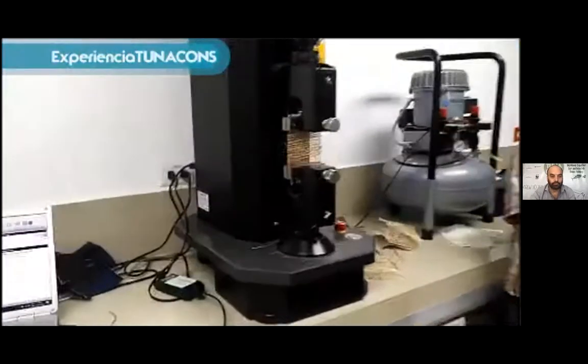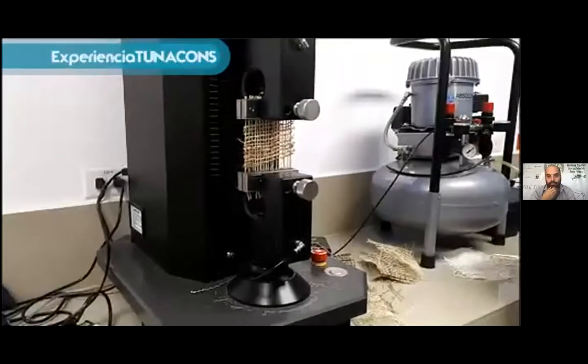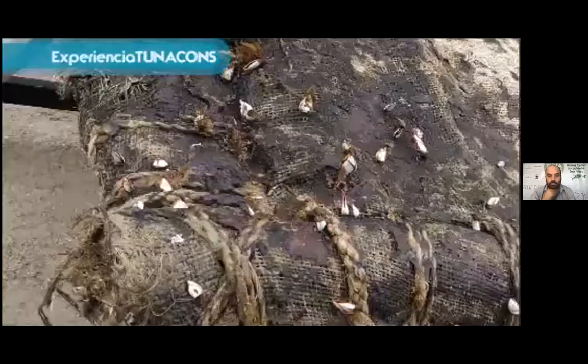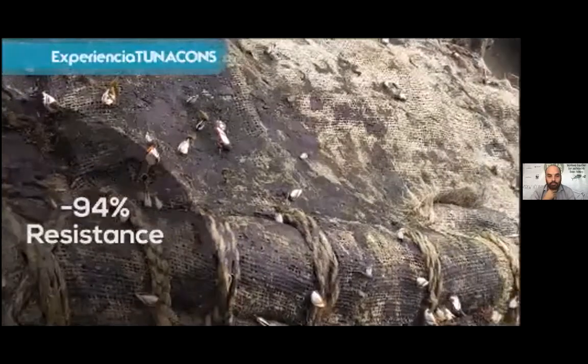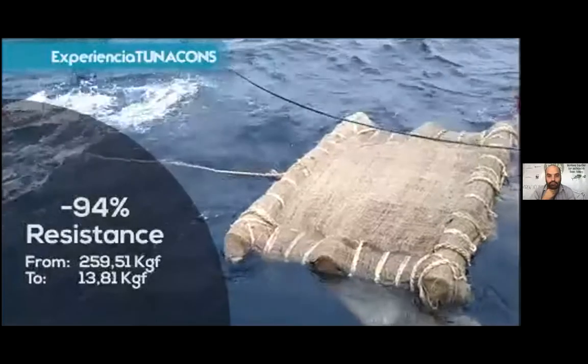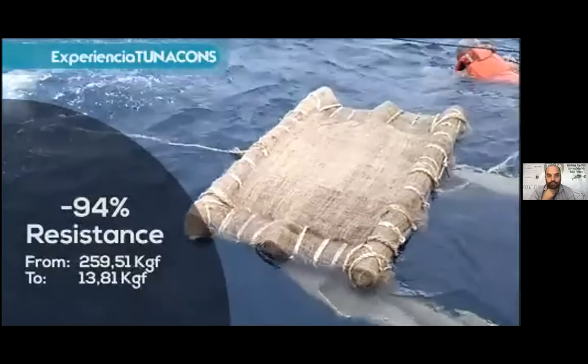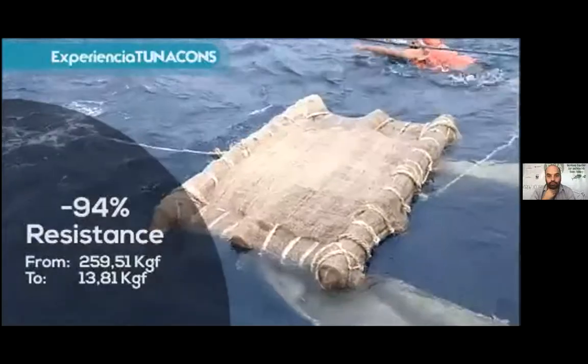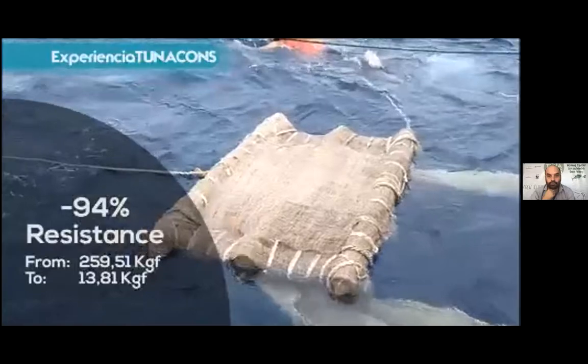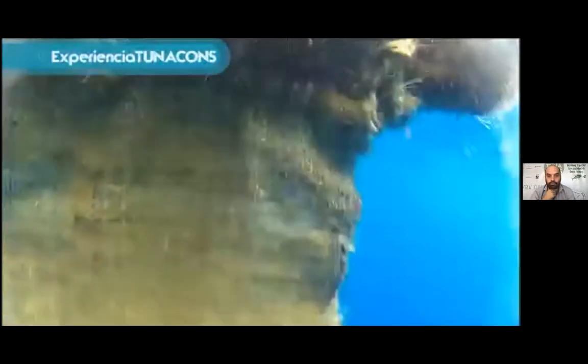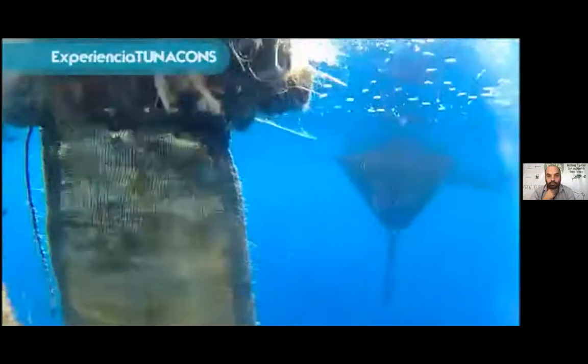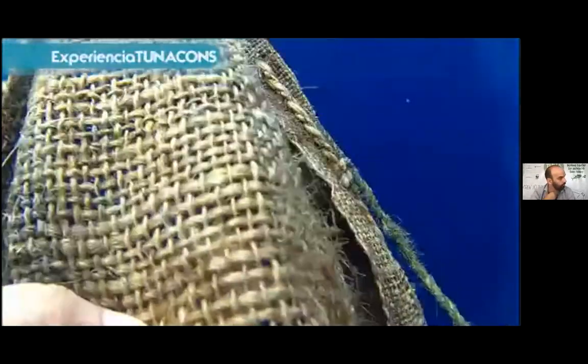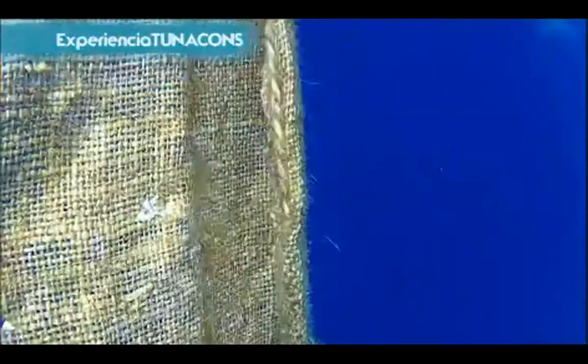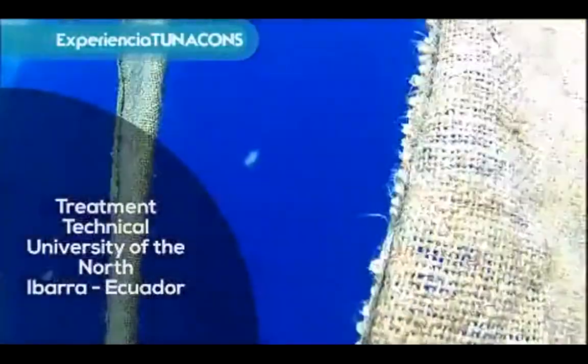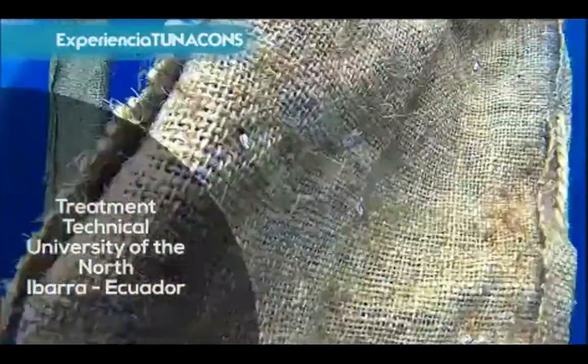With the Technical University of the North in Ibarra, the abaca fiber was analyzed and the conclusions were as follows. After 67 days at the sea, the abaca fabric lost 94% resistance because before the deployment, abaca had 259.51 kilogram force, and in the fourth monitoring, its breaking strength had dropped to 13.81 kilogram force. Among the materials tested by the FIP of Tunacons, the abaca fabric had greater resistance to salt water. And for this reason, the Technical University of the North in Ecuador suggested applying a process to the fiber for protection in the alkaline medium, since previously raw fiber had been used without any processing. They proposed to give it a special treatment with the projection of extending the useful life of the material.